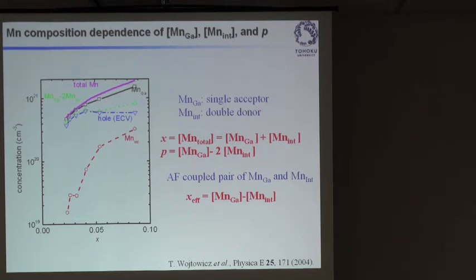First of all, manganese in the gallium site is an acceptor. Manganese in the interstitial site does not have any bonding, which means it has two s electrons which can be donated to the conduction band of gallium arsenide, and as such, manganese interstitial is a double donor. And the total manganese concentration in the sample is divided into manganese sitting in the gallium site and manganese sitting in the interstitial site. And the hole concentration is given by this equation. Because interstitial is a double donor, it emits two electrons and it can kill two holes, which means that our hole concentration is not only the difference between the two, but this difference minus two times manganese interstitial.